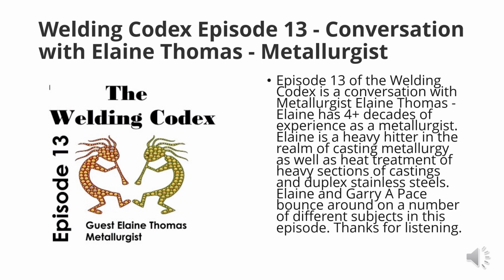But as far as proving a heat is good or bad, I don't think it's such a good test, mainly because it's based on weight loss, and if even the smallest little inclusion falls out, your weight loss jumps through the roof. And I guess that's a problem with welding too. If you have a little bit of slag in there and it falls out, it's going to be a real bad test, and you're going to end up spending a lot of money. So the material you use has to be really clean.